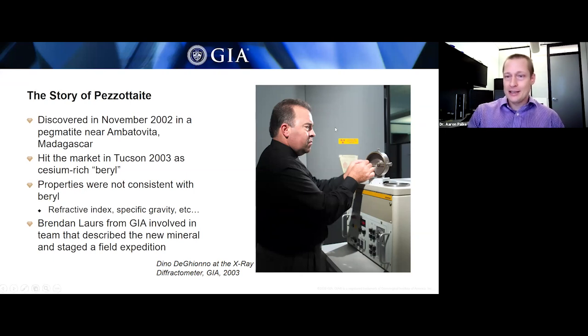Dino DeGhionno is shown here at the X-ray diffractometer we used to have at GIA back in the day. While we use Raman spectroscopy to identify unknown minerals today, back then they didn't have a Raman spectrometer, so they would have turned towards X-ray diffraction. What you would see, this was an older unit where they actually used actual film in this canister that Dino is loading. So he's loading up a small bit of this mineral on a spindle inside this canister. He would have put film around the outside edge of that canister, and they would shoot X-rays into this stone, and then you would get a diffraction pattern on that film.